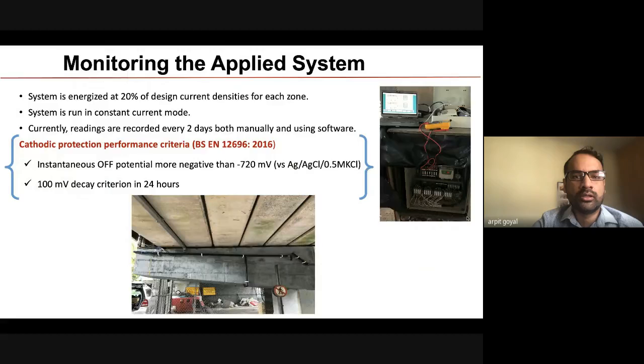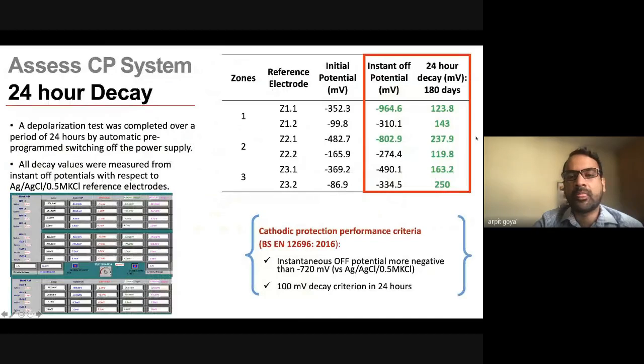So we could see that it's satisfying the required performance criteria, that is about minus 720 millivolt instantaneous off potential, or 100 millivolt decay in 24 hours. So either of these criteria need to be satisfied for a successful system. And you can see from the table above, it is satisfying either of these two criteria. And the system is performing well even after seven months now.